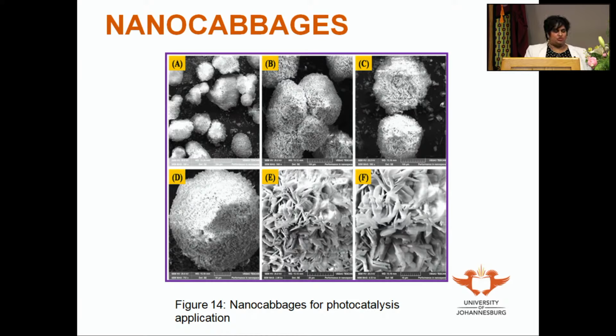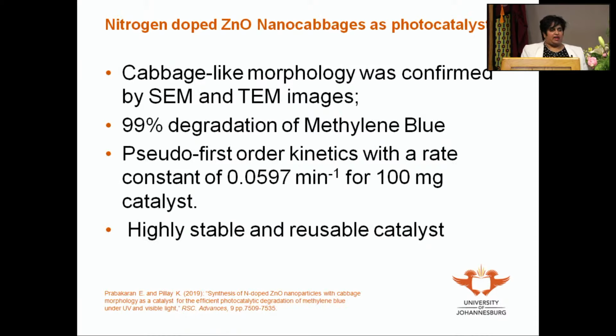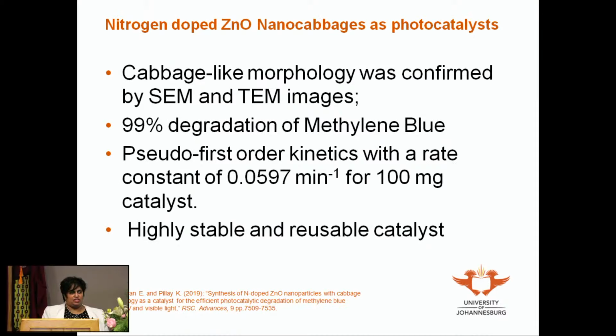Now coming back to the nitrogen-doped zinc oxide nanocabbages that we prepared. We actually prepared this for a photocatalytic application. And we used methylene blue dye as our model organic pollutant. We found that it was highly effective for the removal of the dye. And we found that it was quite a stable and a reusable catalyst as well.